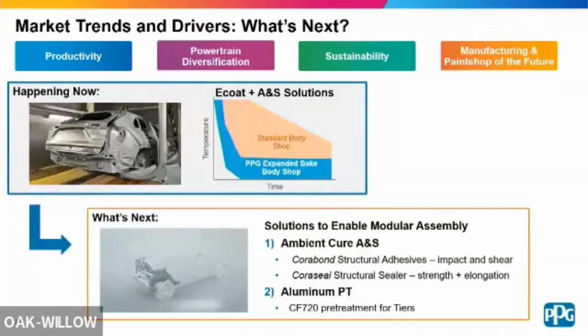Okay, another one online. Is there an impact on target film thickness with the Epic Low Cure Ecoat product? So we actually have a wider range because our friends in EMEA, I'm global, so I have to worry about everybody, their target is much lower than what America is. It's about half. So the range is like 35 to a standard. We have some OEMs that want to go down to 30. We have one that's like, can we do 28? So we're even looking at that. So we're going to go pretty low on this product if we can, which we will.